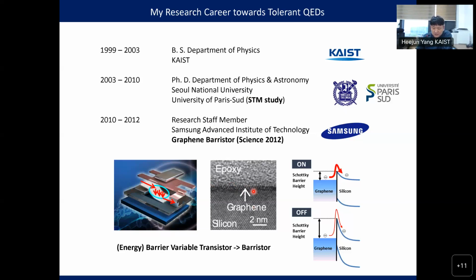If we make this special Schottky junction, this is a Schottky junction between a semiconductor, silicon, and a semi-metallic graphene. We have a Schottky barrier height like this. But you know, in graphene, we have quite a small density of states. So if we